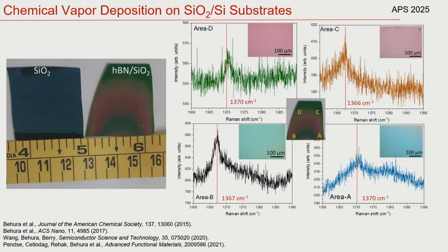But we were successful. We were actually able to deposit our hexagonal boron nitride directly onto silicon oxide. And with that one-step process, we were able to take that substrate, readily characterize it with Raman, and then after confirming that hexagonal boron nitride was on the surface, as you can see here, peaks around 1,366 relative inverse centimeters denote hexagonal boron nitride. And these variations around 1,366 often denote the number of layers. So not only were we able to get hexagonal boron nitride on the surface, we were actually able to manipulate the thickness of growth that was occurring, that we're hoping to tune more and more as we continue on in this process.